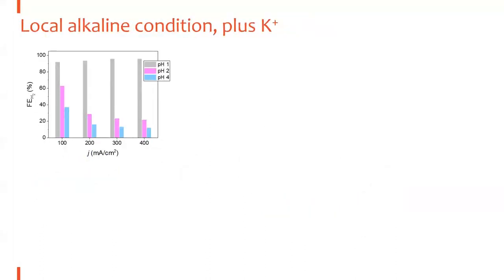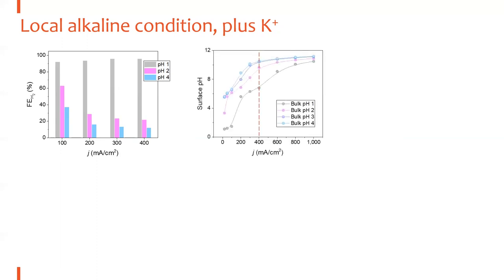So we tested our modeling by doing experiments, and we used different pH, from pH 1 to pH 4. We found that for pH 2 and pH 4, we can observe much reduced hydrogen evolution reaction. But for pH 1, what we observe is still only hydrogen. So how can we understand this phenomenon? We go back to our modeling result.